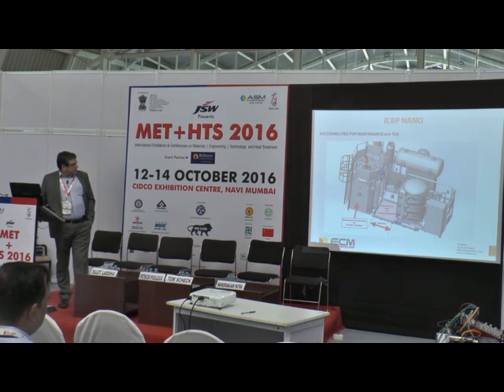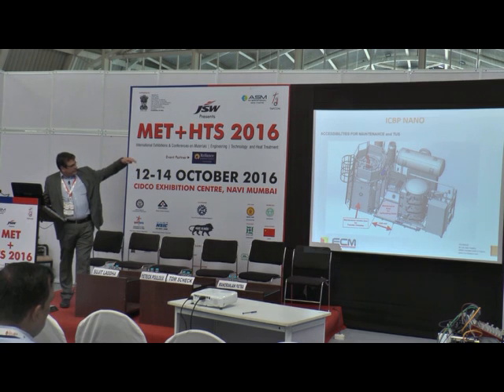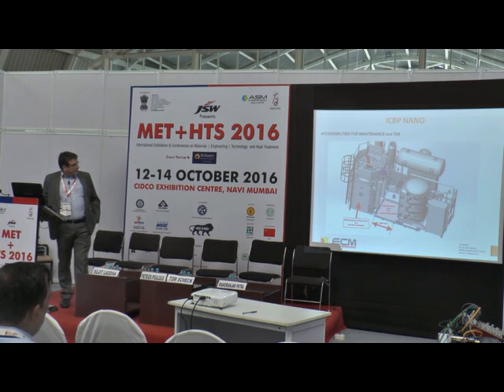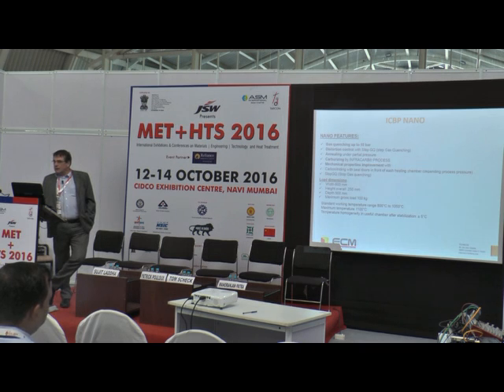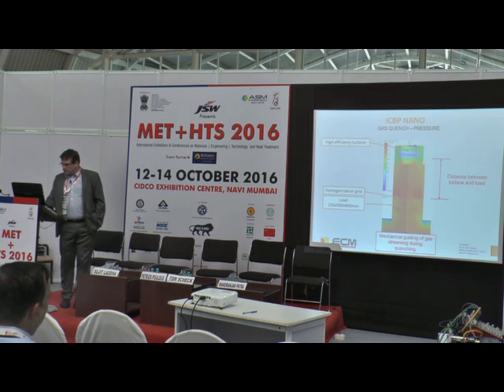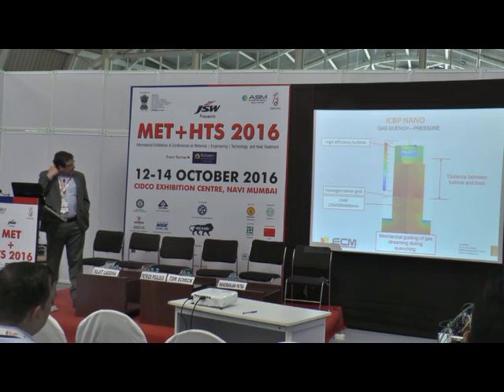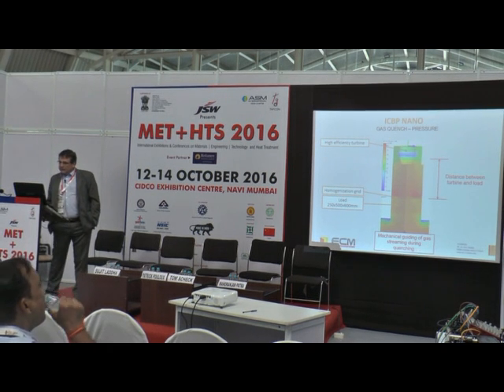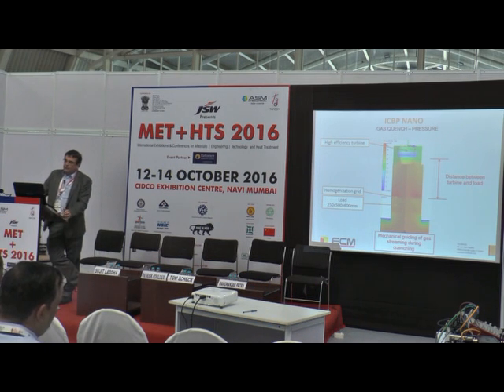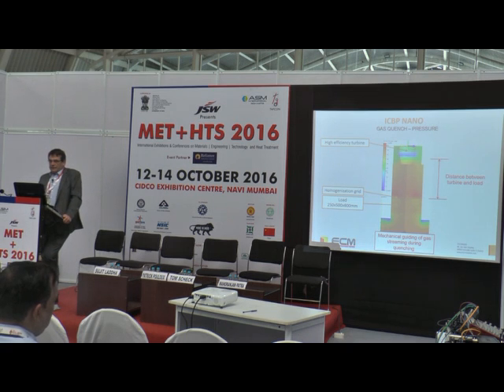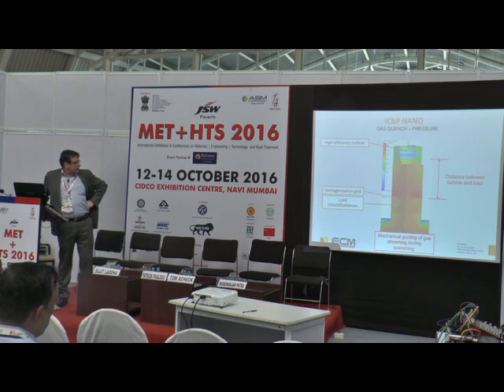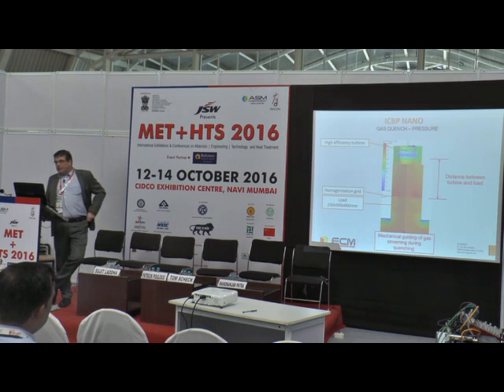Here you can see the furnace in the middle. This is the transfer room. And at the back we have the 10 bar gas quenching. What is important for this part is to have a very homogeneous speed of the gas flow, which is achieved thanks to a certain distance of the load to the high efficiency turbine, and we have a grid to have a better distribution of the gas speed. Thanks to that, I have sold at least 7 to one big German company, and they treat in bulk some small pieces made of non-alloyed steel.